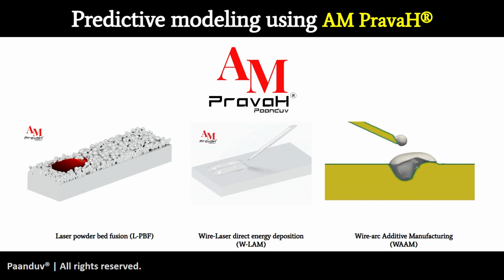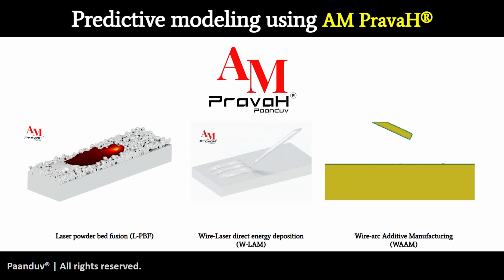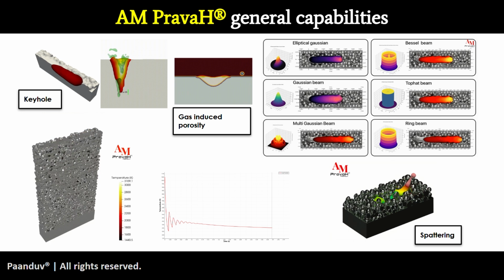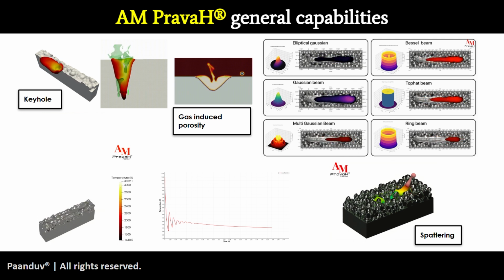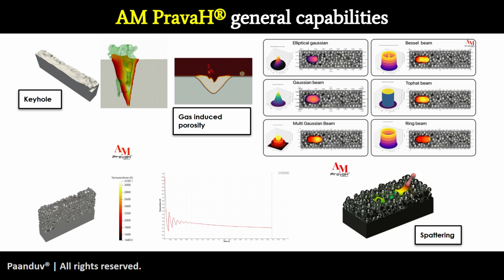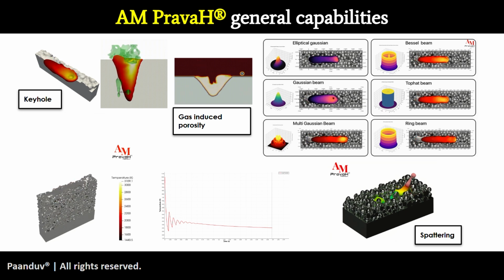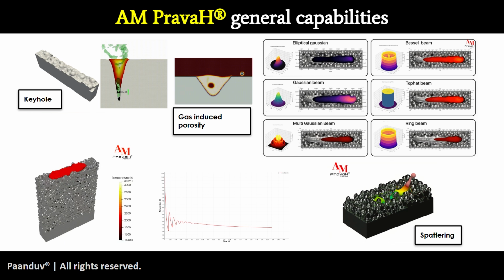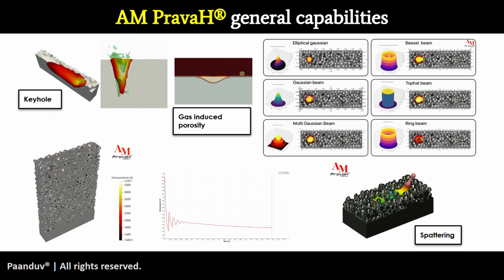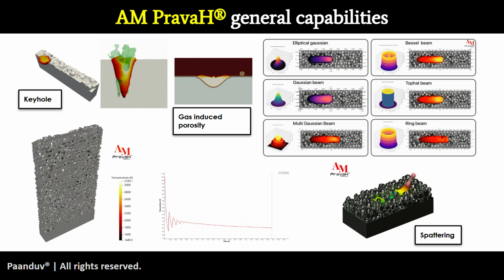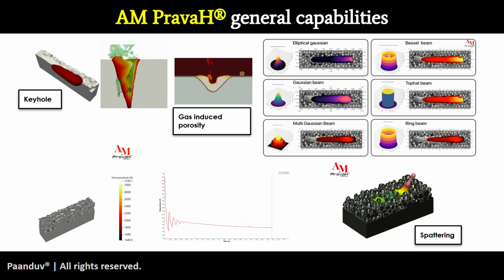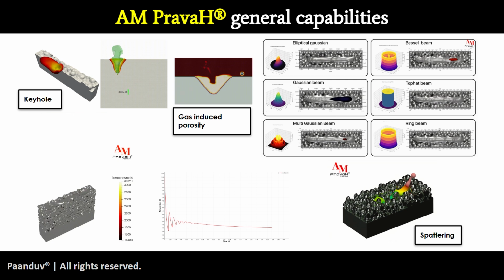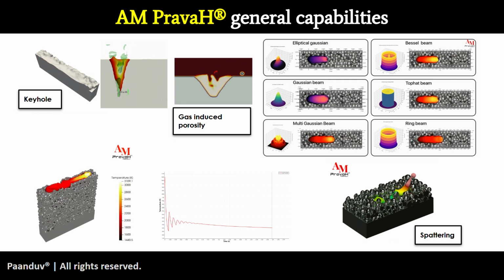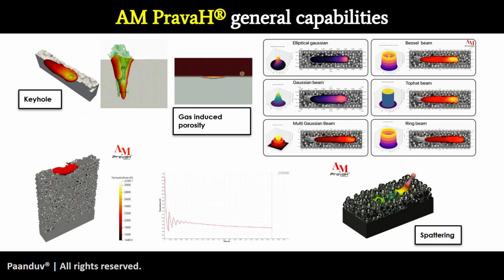So in AM PravaH currently, laser powder bed fusion, wire laser additive manufacturing, and wire arc additive manufacturing processes are captured in great detail. Some of the general capabilities of AM PravaH, of course, include the keyhole estimation, keyhole simulations, gas-induced porosities, multi-layer thermal contours, where you want to understand after how many layers the effect of the current built layer is eliminated on the bottommost layer. So you can see on the plot here that after 9 or 10 layers, the effect has gone away, based on the thermal cycling plot here.